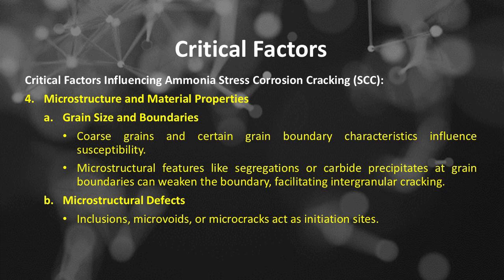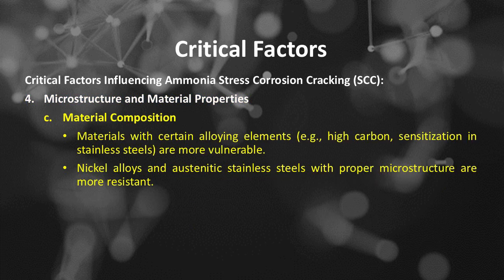Number B, microstructural defects. Inclusions, microvoids, or microcracks act as initiation sites. Number C, material composition. Materials with certain alloying elements, such as high carbon, or sensitization in stainless steels, are more vulnerable. Nickel alloys and austenitic stainless steels with proper microstructure are more resistant.